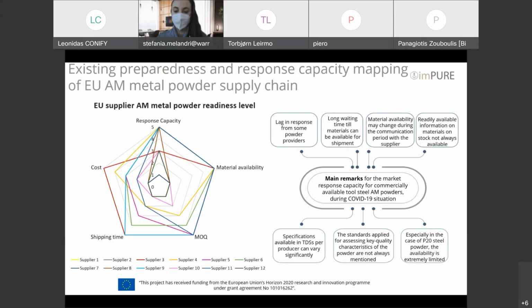So the chart shows the different factors: response capacity, material availability, minimum order quantity, shipping time, and costs. These were the main parameters we examined. And we observed that there was a lag in the response from some powder providers, a long waiting time until the materials are available for shipment. Of course, the availability of the material might also change during the communication period with the supplier and the procurement of the powder.